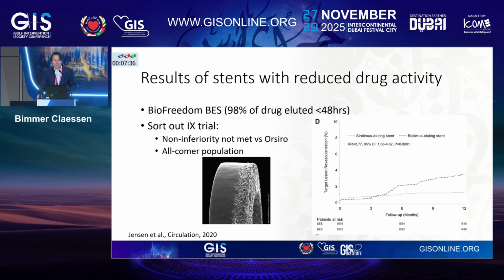Now, what happens if a polymer-free drug-eluting stent does not have these favorable drug release kinetics? Well, this was seen in the SORT OUT IX trial, where the polymer-free BioFreedom stent was compared against the Orsiro drug-eluting stent in an all-comer population. These were more than 3,000 patients. It was supposed to be a non-inferiority trial. However, non-inferiority was not met for these patients. And that was mostly because of an increase in target lesion revascularization with the uncoated polymer-free BioFreedom stent, which had TLR rates which were almost 3 times as high as the Orsiro stent.